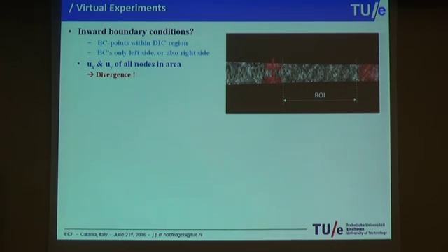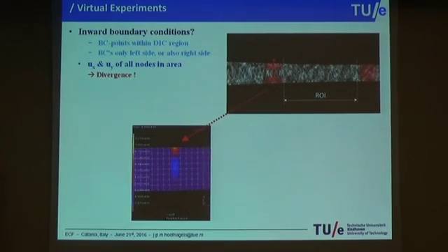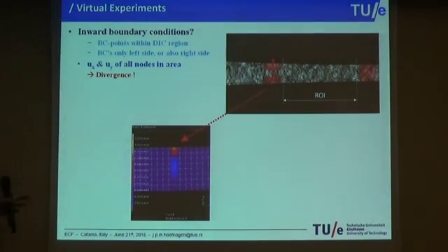This doesn't work. So it is really sensitive to these boundary conditions. So what could we do? The reason is that if you have boundary conditions that are, for instance, working in the same direction, and if you first have to determine them with DIC locally in this region, just a small error gives you huge stresses locally, and they work inwards into your region.